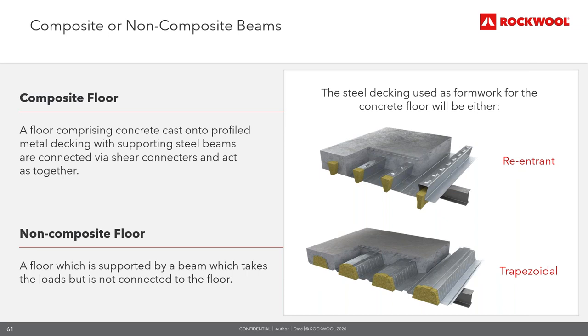However, it's not always possible, once it's all in place, to determine whether it is composite by a visual inspection only. Therefore, in a building where the floor slabs are already in place, confirmation would need to be obtained via an appropriate engineer, or alternatively, if it's not possible to determine whether the beam is composite or not, then all voids above the flange would need to be filled. The steel decking used as formwork for concrete floors will either be re-entrant or trapezoidal.